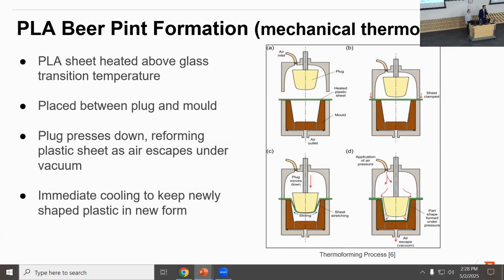So the actual beer pints that you guys have probably seen at Extra Mile Arena before are formed with a process called mechanical thermoforming. What happens is a sheet of PLA is taken above its glass transition temperature and placed between a plug and a mold part, and then the plug goes down as air is released to allow for cooling and for the solidification of this heated PLA in the newly formed pint mold. And it's immediately then sectioned off through machinery to mass produce it.